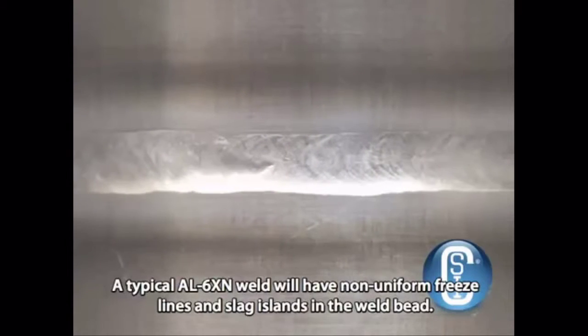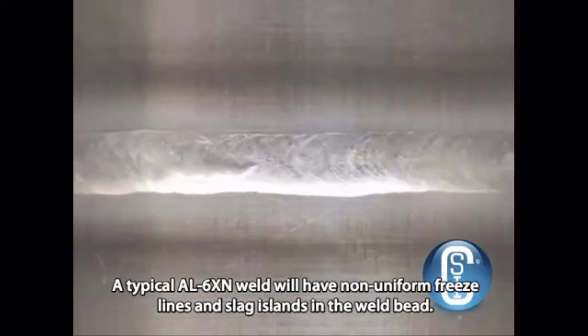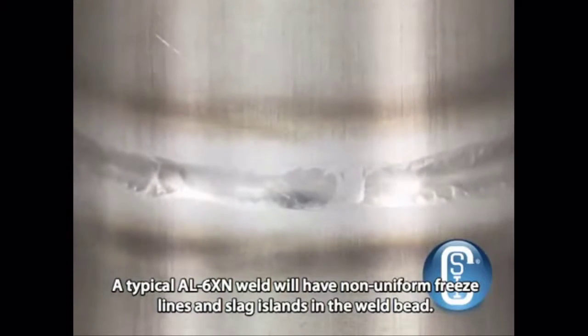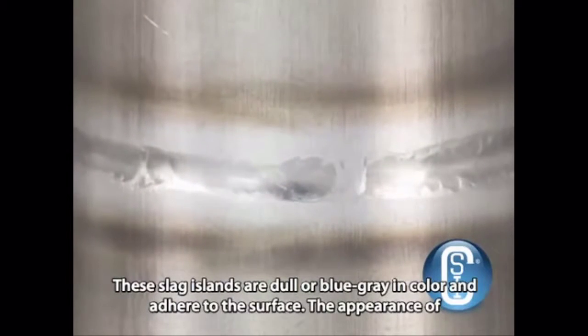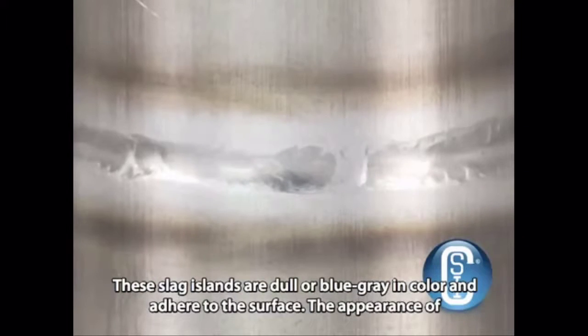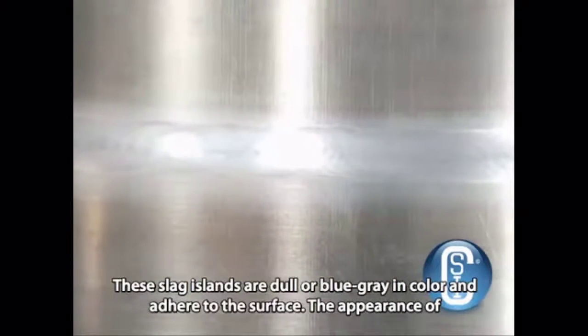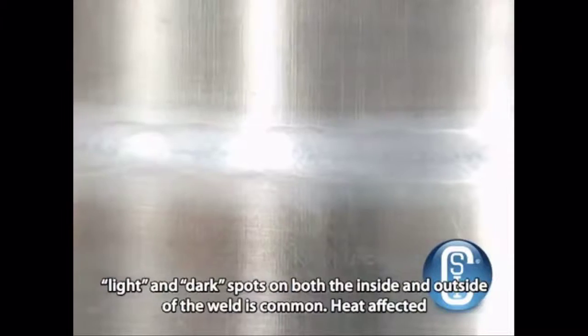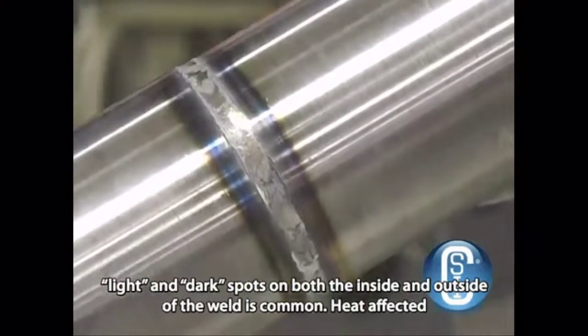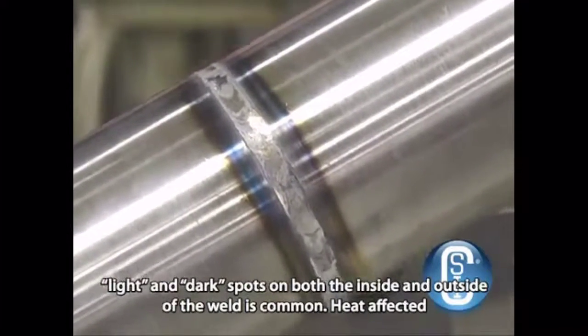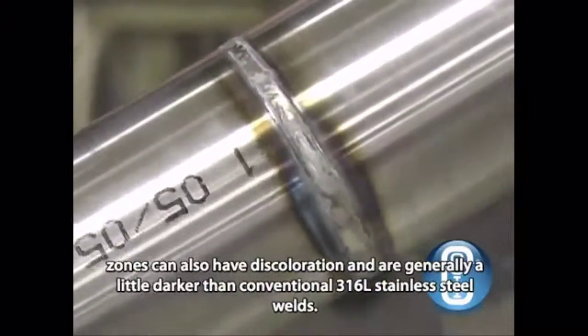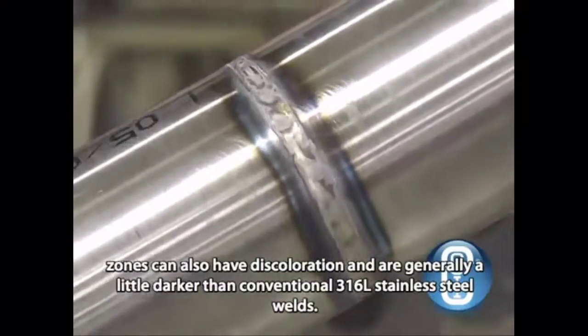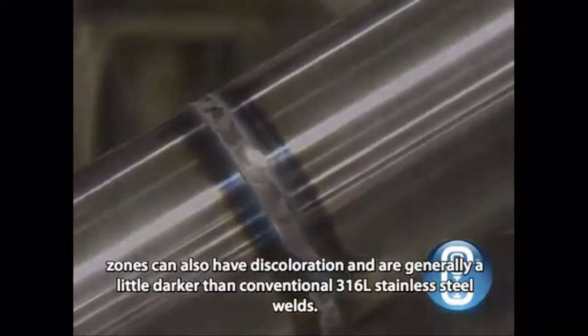A typical AL-6XN weld will have non-uniform freeze lines and slag islands in the weld bead. These slag islands are dull or blue-gray in color and adhere to the surface. The appearance of light and dark spots on both the inside and outside of the weld is common. Heat-affected zones can also have discoloration and are generally a little darker than conventional 316L stainless steel welds.